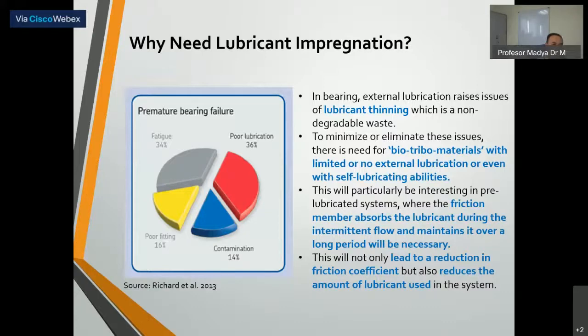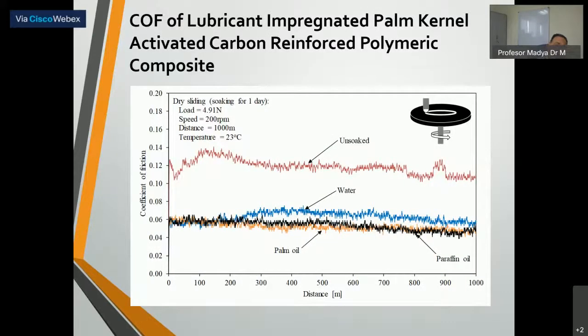Okay, this is the result. We can see that this is the composite without impregnation with the lubricant, and we use three types of lubricant: water, paraffin oil, and also palm oil. With the water impregnation, we can see that there is a sudden increase of the friction coefficient when we arrive around 200 meters. But for the palm oil and paraffin oil, we can see that the coefficient of friction is quite similar. What we can see here is that the unsoaked, non-impregnated composite has a larger coefficient of friction than the impregnated composite.